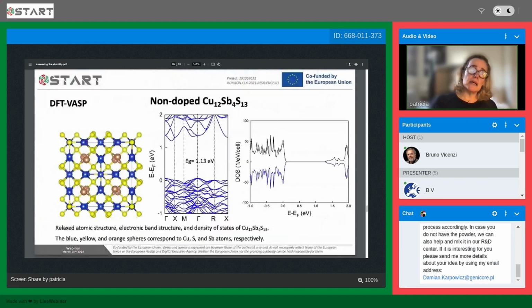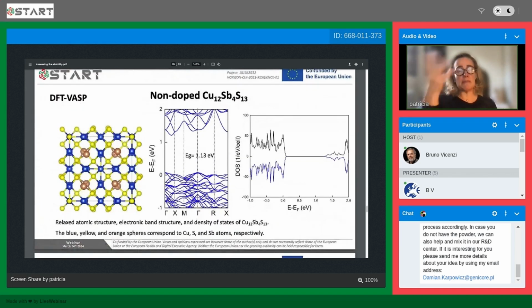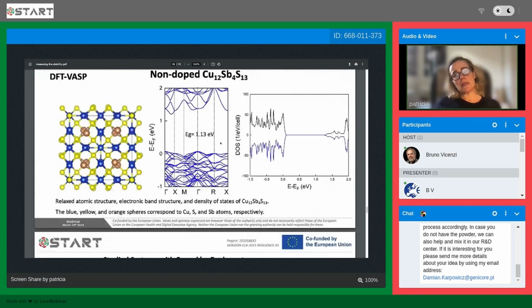Another thing we've done, this is another line of activity related also with the stability and the possibility of the different compositions, is to do density functional theory atomistic calculations in order to try to have some fundamental understanding of the materials. So this is again preliminary results, but we can at least have some trends. So when we apply these methods to pure tetrahedrite, non-doped, we see that we have quite a large band gap. It's not exactly the value which is published, but it's interesting to compare.